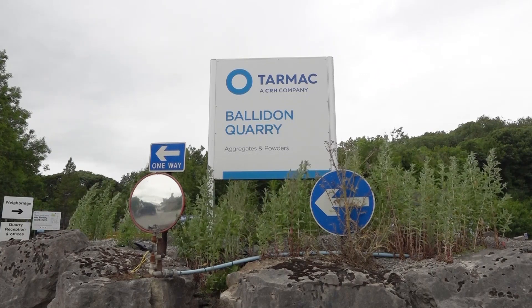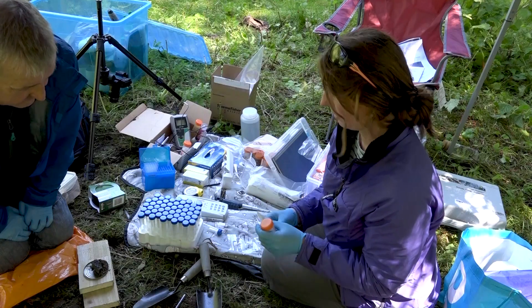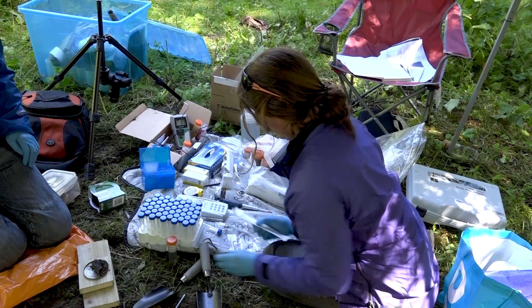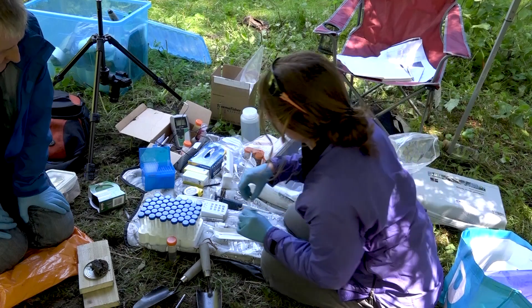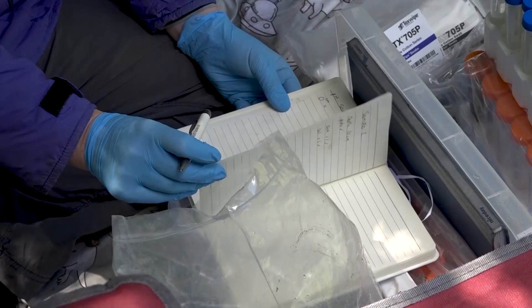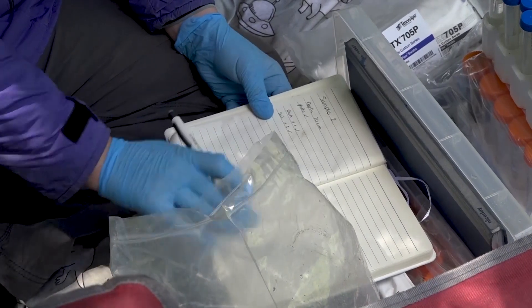Unfortunately, we have lost track of the Wareham samples. But the Ballidon samples continue to be useful from the point of view of nuclear waste disposal, because we expect the pH in a future subsurface repository to be alkaline — both because of the dissolution of glass raising the pH, and also because of the dissolution of cementitious material in a geological repository.